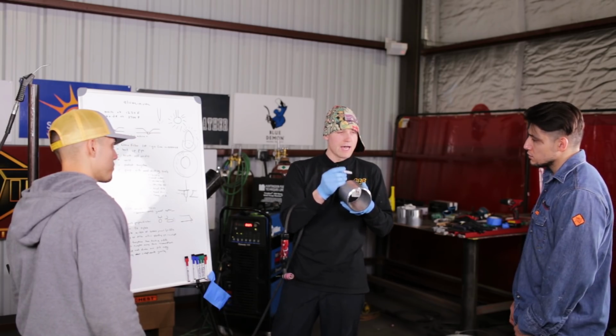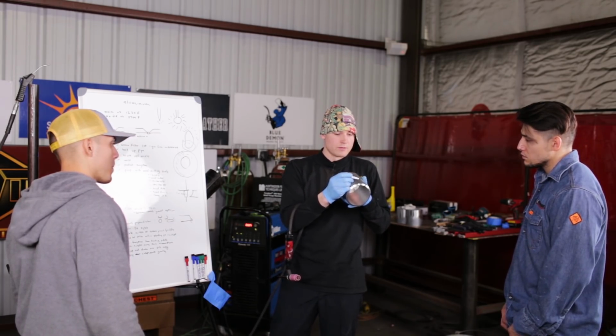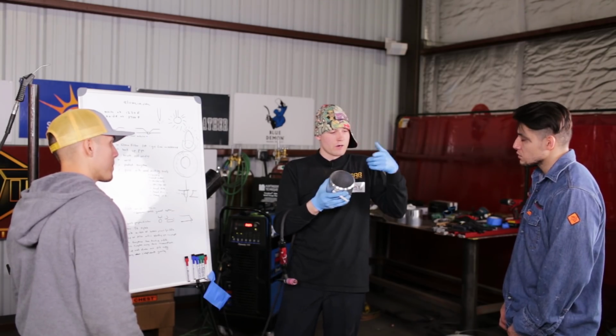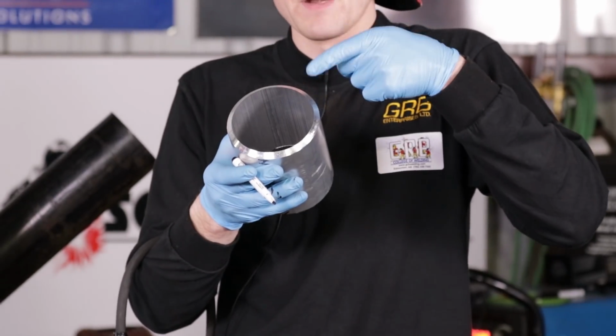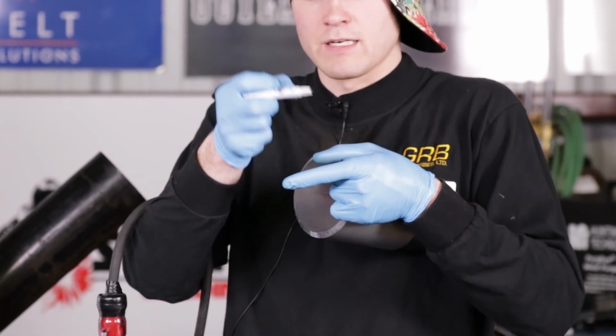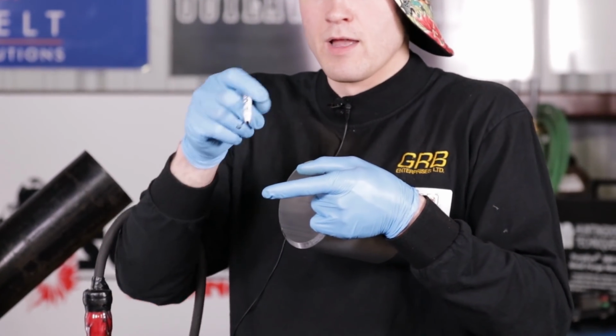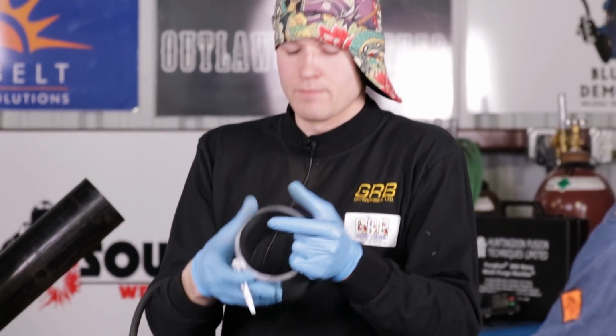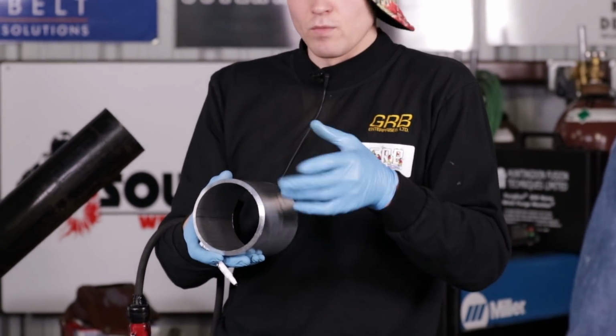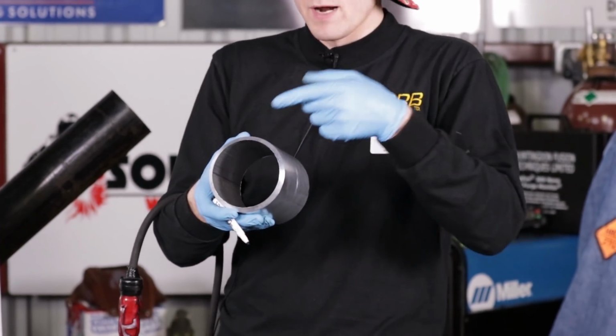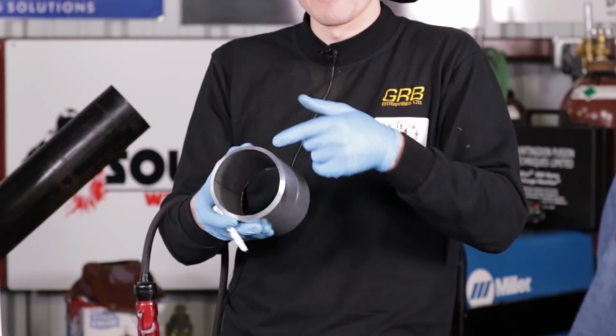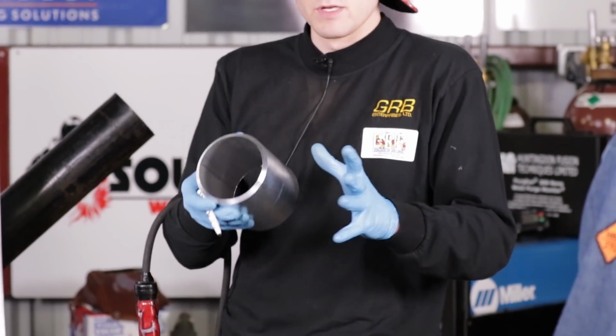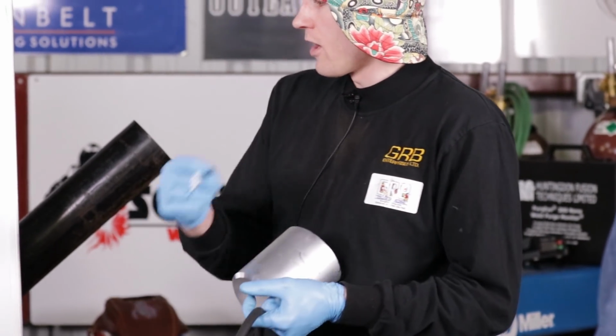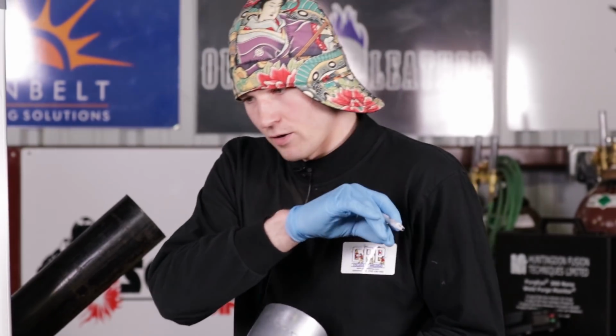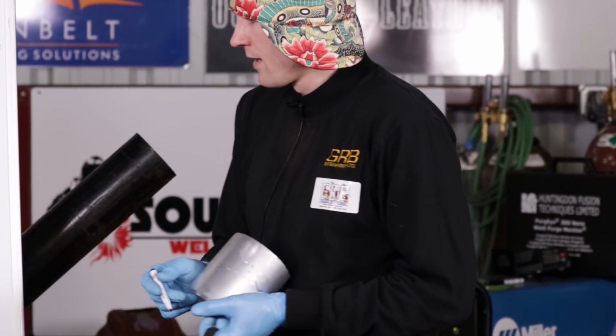And when it comes to adding fill metal, you're going to be doing an up and downward motion. So you're on the leading edge or in the middle of the puddle, but it's always an up and down motion. That way you're always protected within the shielding gas, within the atmosphere of the ceramic cup. Some guys, you can watch them, they may pull away rather than up and down. They're removing the tip of the fill metal away from the shielding gas of the ceramic cup. So it oxidizes the tip of the fill metal, and then you're reintroducing oxides into the parent material, or into your weld puddle.